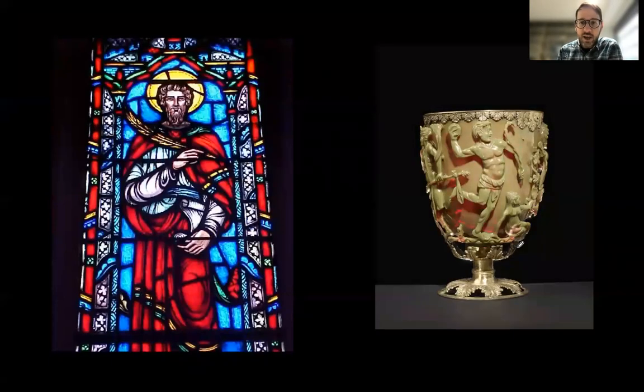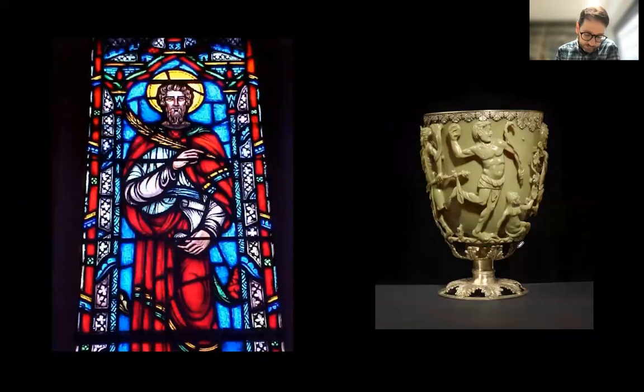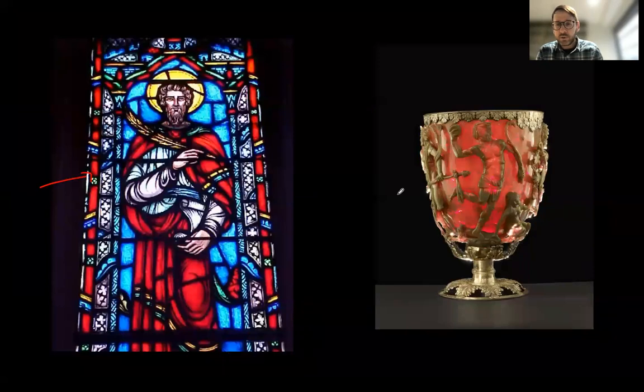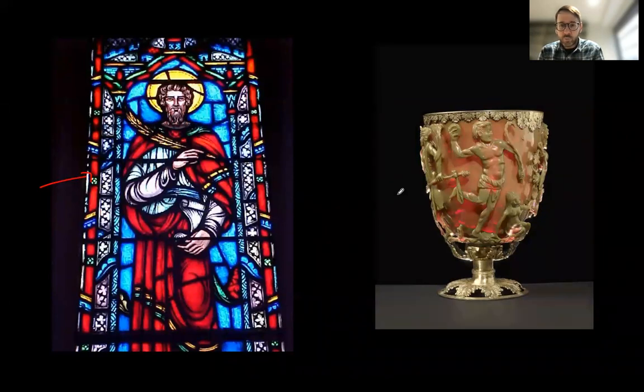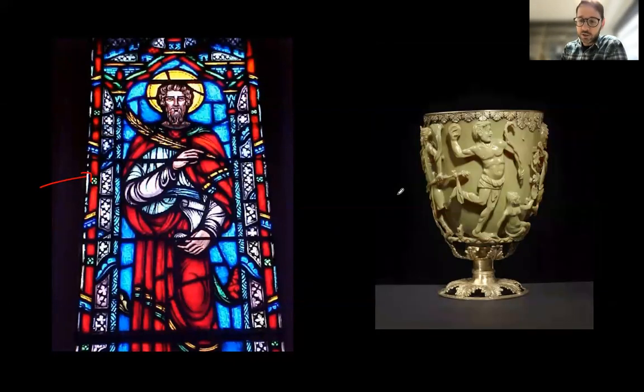And in fact, since ancient times, these interesting colors of gold nanoparticles have been employed to give colors to these glass windows. So the red colors here are made of gold nanoparticles, and this remarkable example of the Lycurgus cup made by the Romans, in which we have an interesting dichroic effect. As we shine light from inside the cup, we see red due to these absorption and scattering properties of gold, and then if we shine light from the outside, we see green. So the green corresponds to scattering, and the red corresponds to absorption of light, actually. And this has in the composition gold and silver nanoparticles, and not only gold, actually.